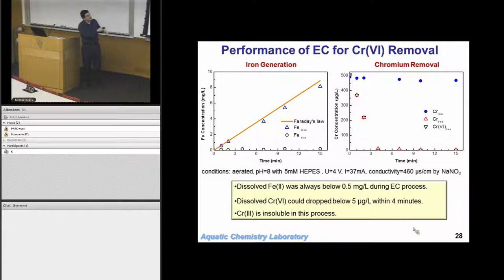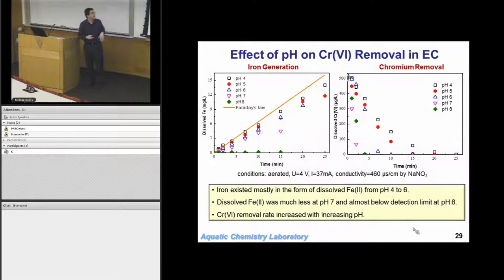Total chromium stays the same. That's total dissolved plus suspended. We're getting it out of water, and we're getting the chromium 6 out of water. So this definitely works. We're now understanding how this works. It's affected strongly by pH. I'll point your attention maybe mostly over to this right-hand side. So the pH 8 data we just saw is in the green. Like 4 minutes, very low. pH 7, it also works quite well. Not quite as fast as pH 8.